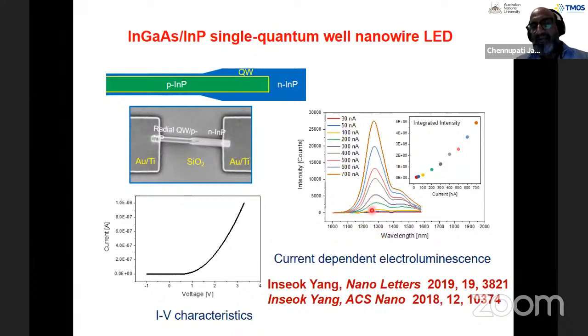But fortunately, the light emission peak is taking place in the 1.3, 1.55 micron window region. That's a window region which is important for optical fiber communications. So you can see that though light intensity is increasing, there's no narrowing of the linewidth, no threshold-like behavior from these output characteristics, indicating that they're acting like light-emitting diodes, not like lasers.